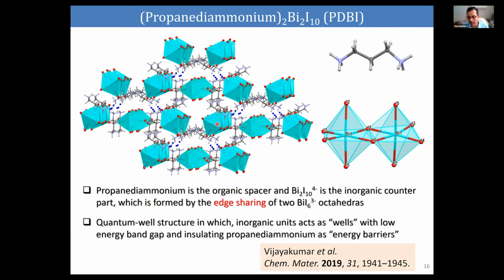Here we found that the edges of the octahedron are shared in the material, and they formed a very beautiful quantum well structure as we anticipated, because by using less number of the organic cation, actually one side of the three-dimensional structure is not containing the organic cation. So you can see only this direction is having the organic cation, but along the inorganic direction, there is no hindrance created by the organic cation. So the charge carriers can easily hop along that direction from one inorganic octahedron to the neighboring octahedron very easily.